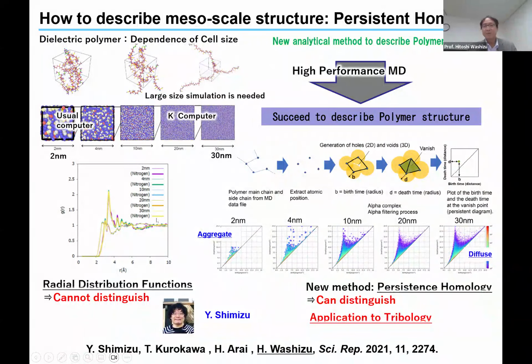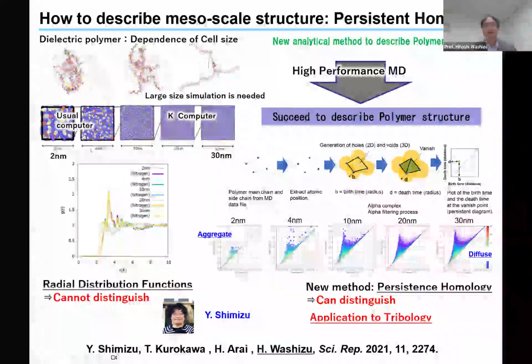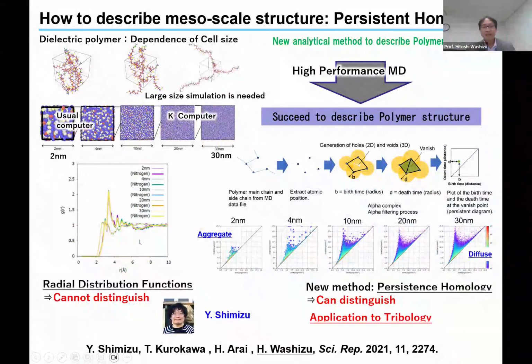It was overestimated in the small cell, and then it goes to a stable value. After that, we'd like to understand what's happening in here and here, okay? But using the RDF, we cannot distinguish this structure. But using a new method named persistent homology, we can distinguish small cell size and large cell size. So this is aggregate and this is diffuse.